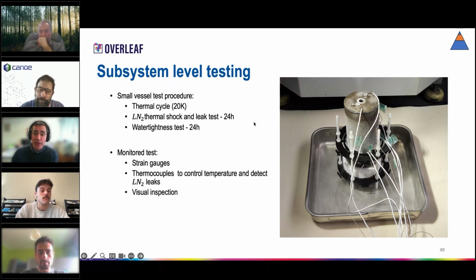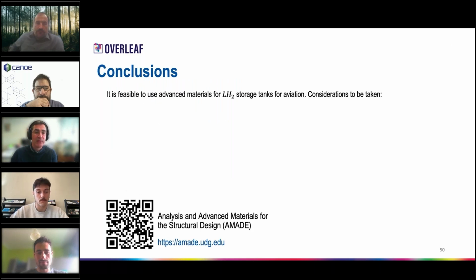This vessel was monitored with strain gauges at different locations, on the top, middle, and at the bottom of the specimen, plus thermocouples during all the three phases to check if there was leakage of liquid nitrogen. This is for safety purposes. This is an open vessel, so here the liquid nitrogen can get out, and we don't have a dramatic increase of the pressure. This is more or less an overview of all the tests that we have performed.